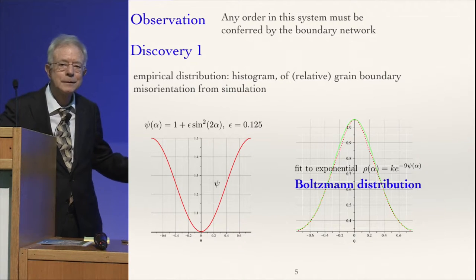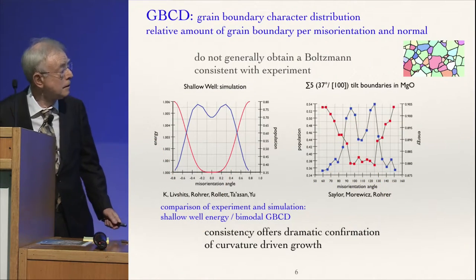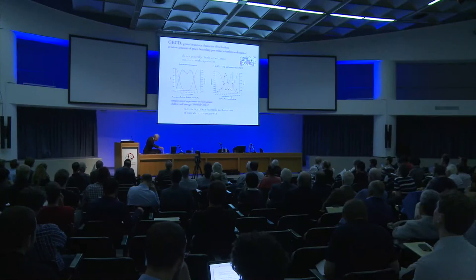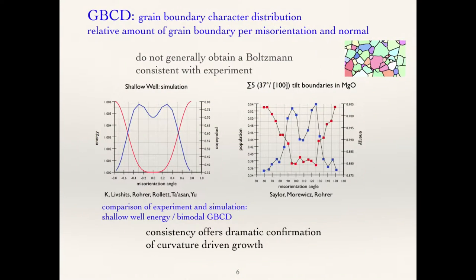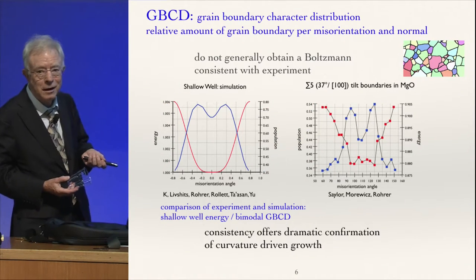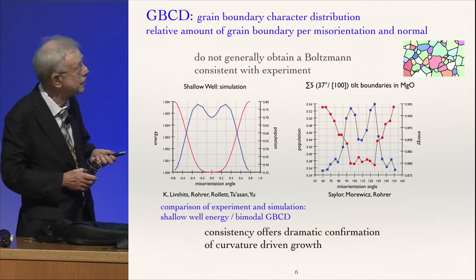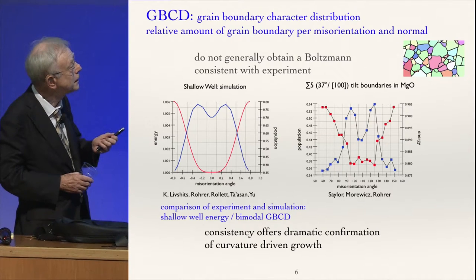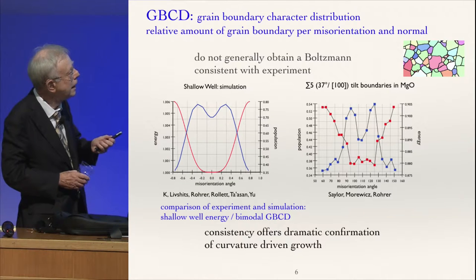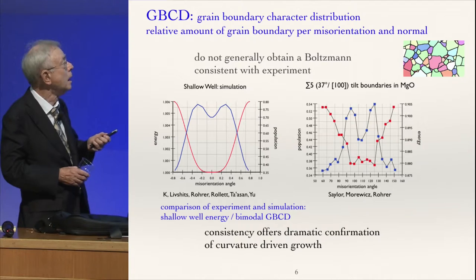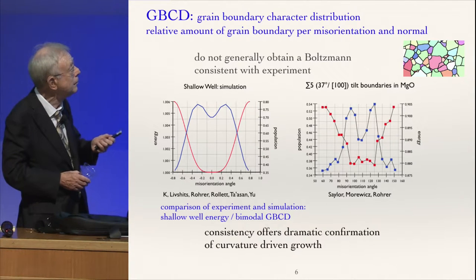So that is one fact, and together with that fact, I want to add a second. So this is the title, but I'll read that later. Here, we simulated an energy which was not quadratic, but just quartic, a sort of shallow well, and obtained a bimodal distribution. Here, on the other hand, you see the result of an experiment different from the pictures which I showed you before, those pole figures. A particularly lucky special experiment where the energy and the population were measured independently. And you can see that for this shallow well energy, there's a bimodal distribution.